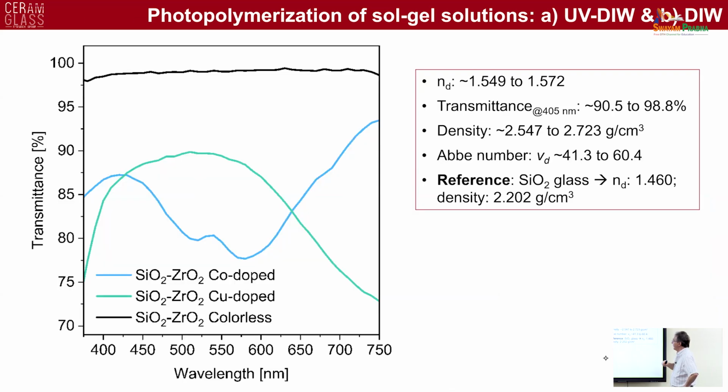You can see here the transparency of the printed glass. And of course, transparency is never 100% because you have reflection at both surfaces. So typically 8% or a certain percentage of light is not transmitted. And then if you add coloring agents, you can have different colors.